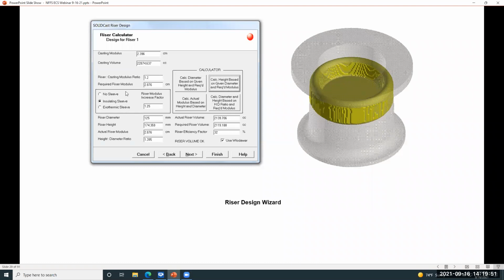We can see here we have the choice of using no sleeve, in other words, a sand riser, or using an insulating or exothermic riser sleeve. And we have a number of options. The system goes through and it verifies 2 things when it's doing a riser size calculation. Number 1, it's doing a thermal calculation, making sure that the riser freezes after the section of the casting that we're trying to feed. It does this by ensuring that the thermal modulus of the riser is greater than that of the casting.